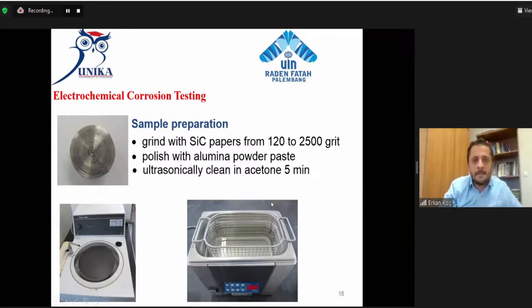And for sample preparation, the samples were ground with silicon carbide papers from 120 to 2,500 grit, and later polished with alumina powder paste, washed with distilled water and ultrasonically cleaned in acetone for 5 minutes.